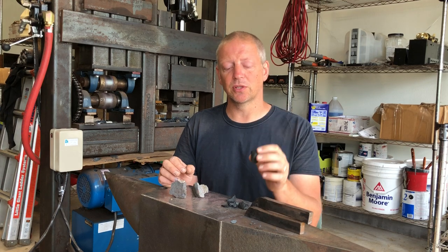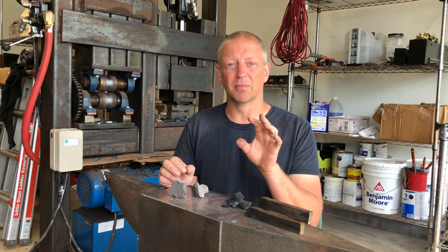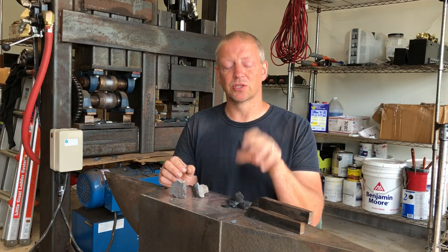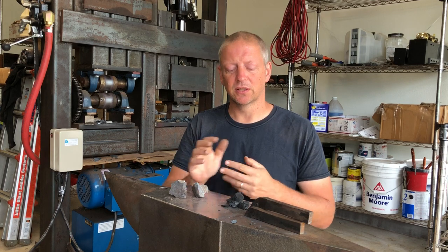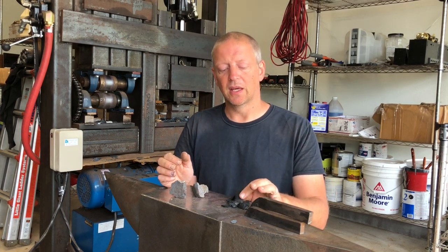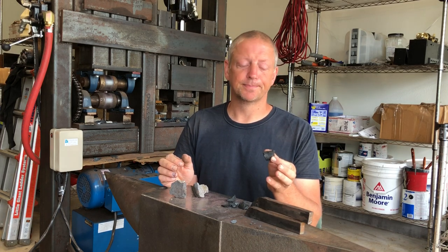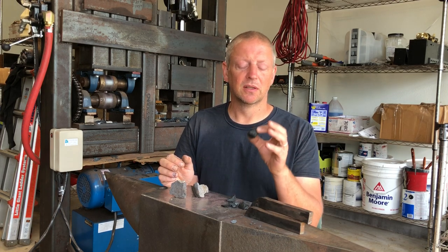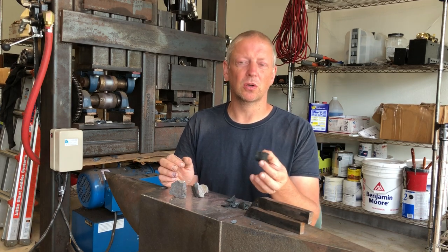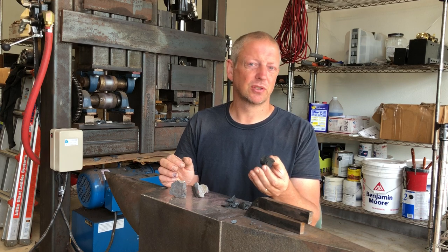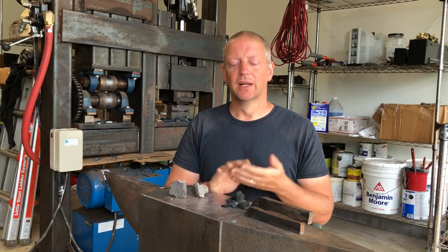It has been cooked at a high enough temperature that you really shouldn't be looking at much phosphorus or sulfur, which are two big no-nos in steel. It will have a small mineral content, but generally speaking, not much of an issue. If you think about burning charcoal, how much actual ash is left when it's all said and done, there's really not much there.